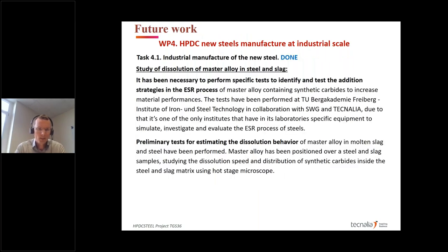That's why we first started to analyze the dissolution behavior of master alloy in steel and in slag samples. It was necessary to perform specific tests to identify and test the addition strategies in the ESR process. For this, we had a strong cooperation with the Institute of Iron and Steel Technology at the University of Freiberg. They have a small ESR available at laboratory level where some pre-trials have been performed. Preliminary tests for estimating the dissolution behavior were also done inside the hot stage microscope.